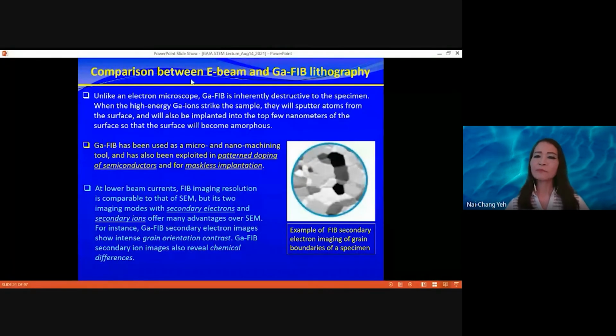or electron beam. And if you compare focus ion beam and electron beam, they have similarities and differences, but gallium ion beam is usually inherently destructive to the specimen. And so if you use high energy, you can remove a lot of material. You can implant the ions into the sample by a few nanometers. And so it's very different. And your surface often becomes amorphous, because you really damage the surface since these ions are heavy. But they are very effective for removing materials. And you can also dope the material, or actually do maskless implantation of ions. But if you use a much lower beam current, then you can do imaging, and the imaging resolution is similar to scanning electron microscopy.